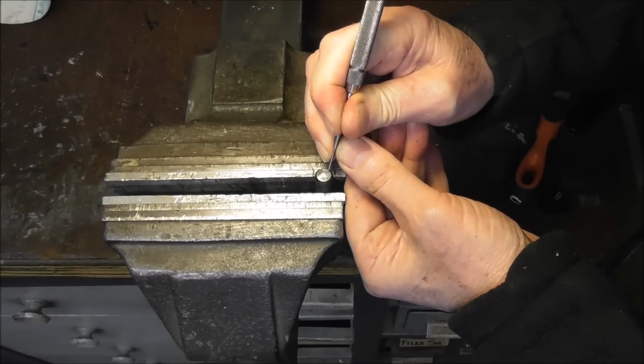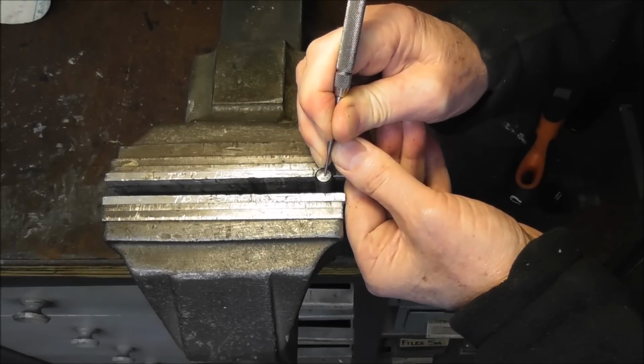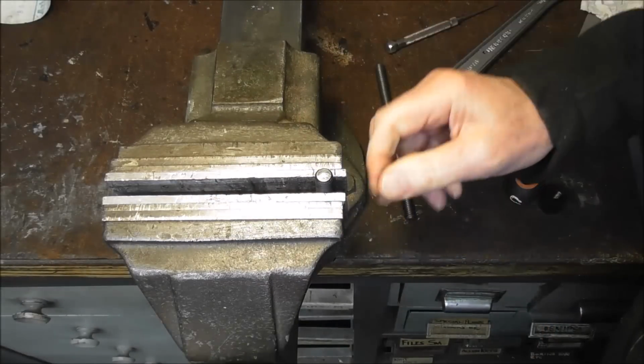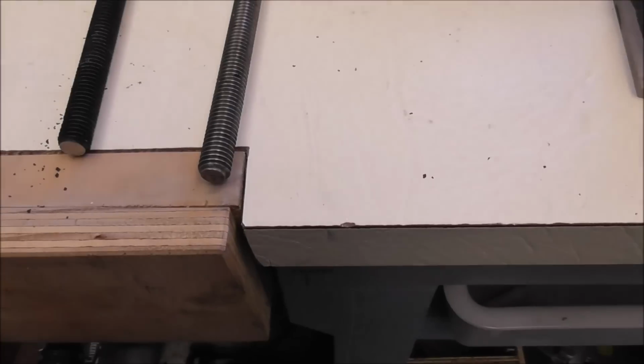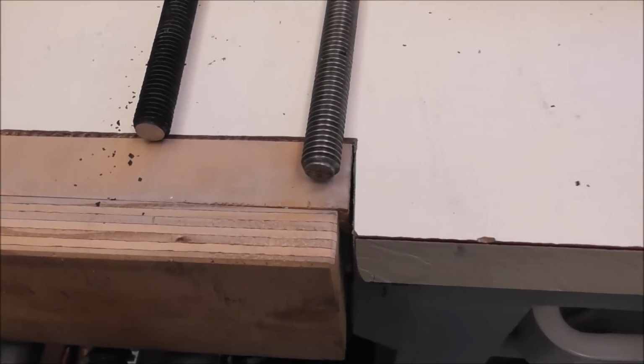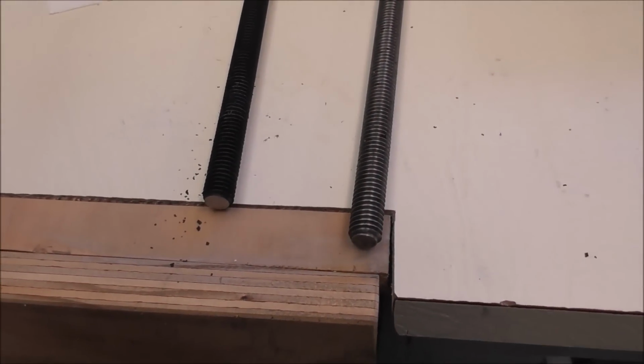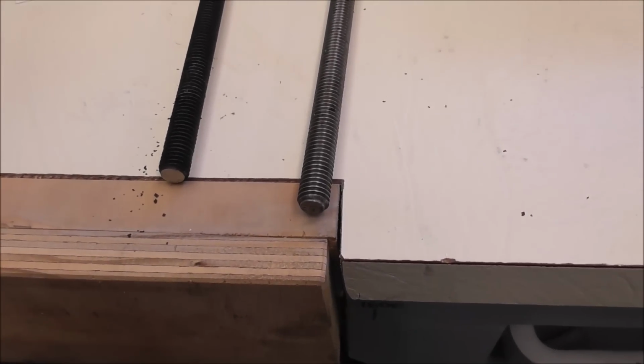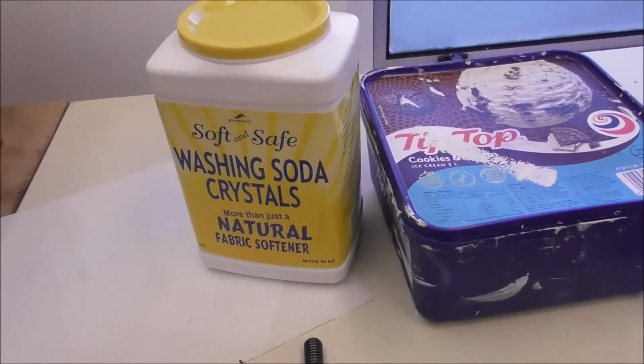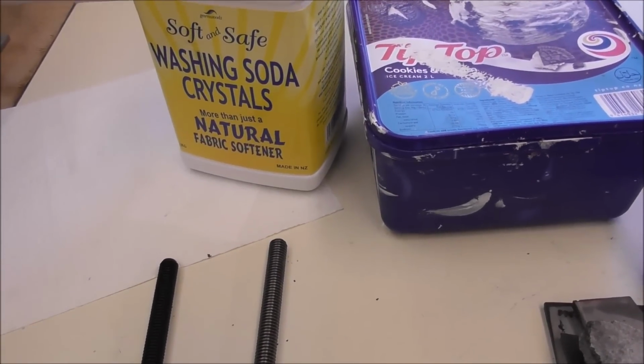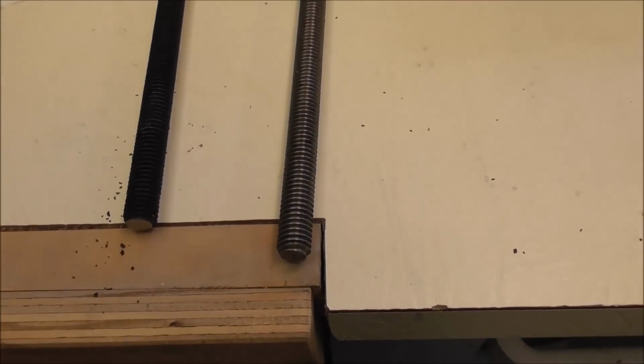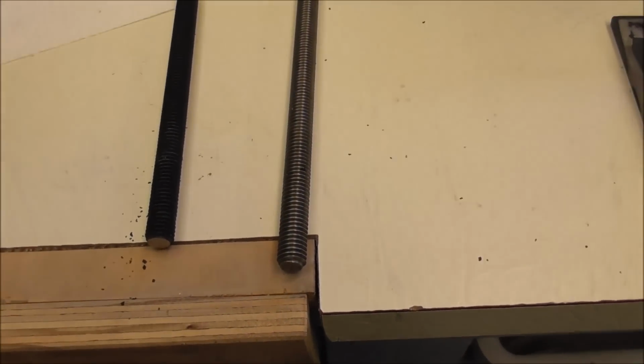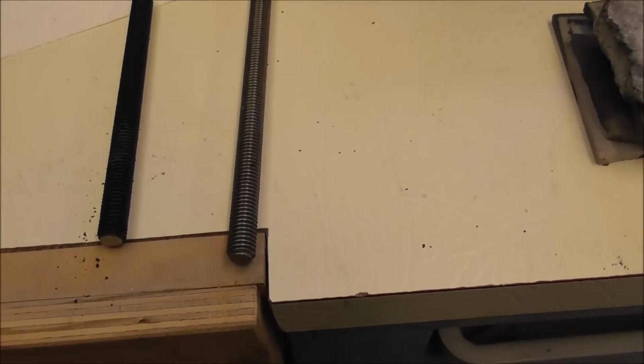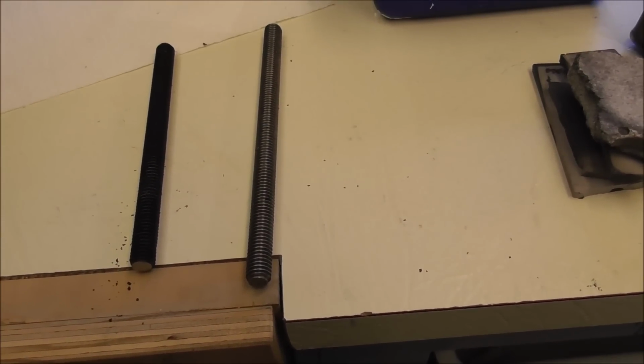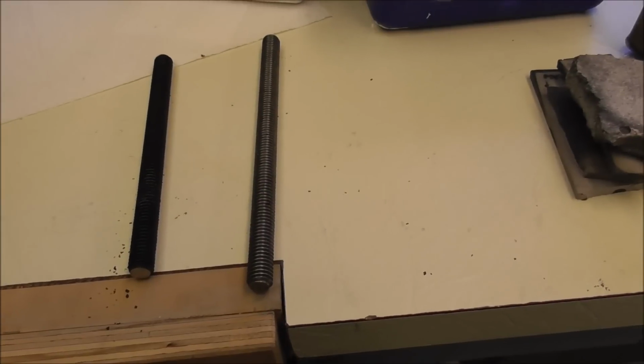Wow, that's so interesting. So it's definitely a very low carbon steel because it is soft in the middle now. I've gone down 0.5 millimeter or 20 thou. Well, that's fantastic news. So that proved that the threaded rod is a very low carbon steel because it's soft in the middle once I get down to a depth of about 0.5 millimeter or 20 thou. So that's incredibly successful. So just using a bit of washing soda crystals and some hardwood charcoal and heating it up, only at temperature for about an hour, it's penetrating in over 10 thou, 0.25 of a millimeter, and just so quickly and effectively that I'm just really impressed with the process, and I'll be using it a lot more in the future, and I'm pleased to be able to pass it on to you guys.